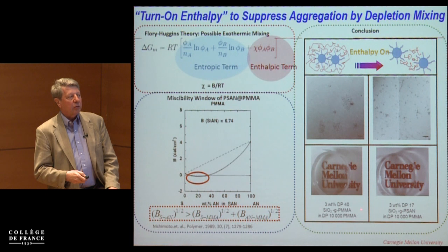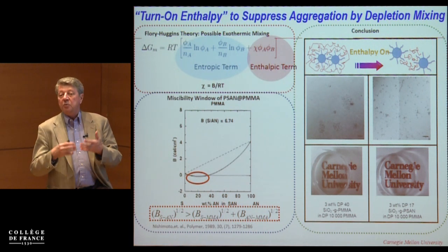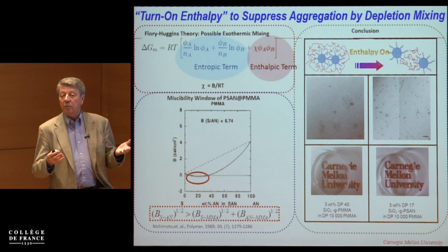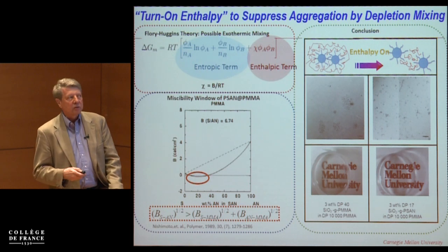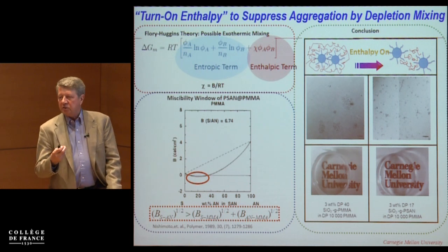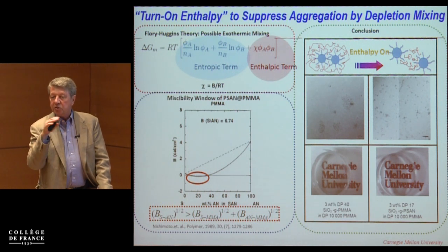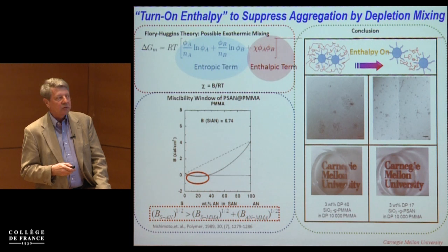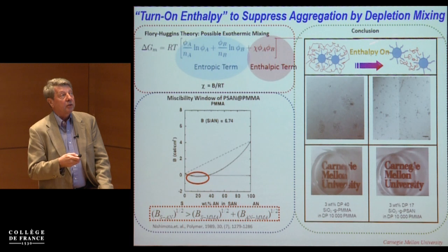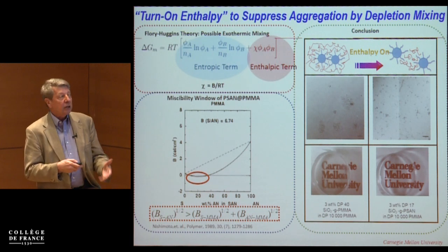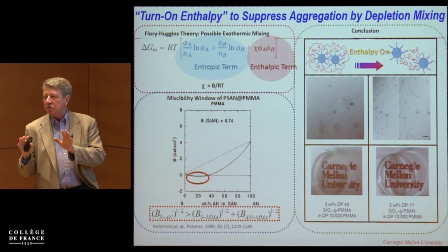And if I have a molecular weight here of 10,000 or 1 million, it means I would need to also have a very high molecular weight brush, which I can do by high pressure, but this is really not that convenient to do. So can I solve this problem somehow? Can I still have nicely dispersed short chains on a silica particle? You need, in that case, an enthalpy component favoring that, because entropy here is against you. Enthalpy means that you should have exothermic mixing. And there are very few examples of polymers which mix.